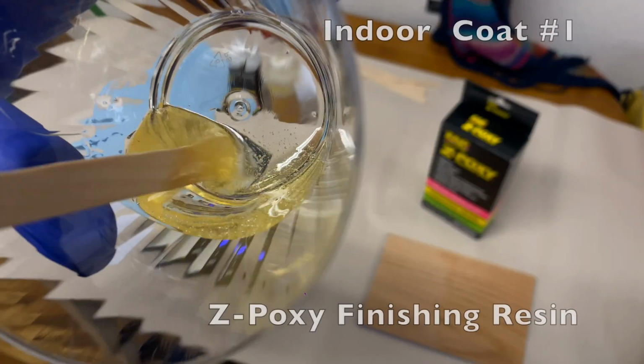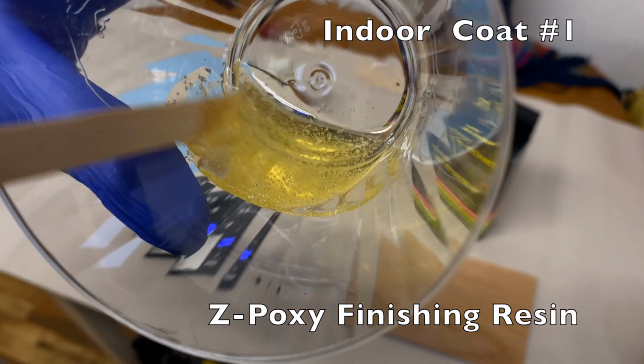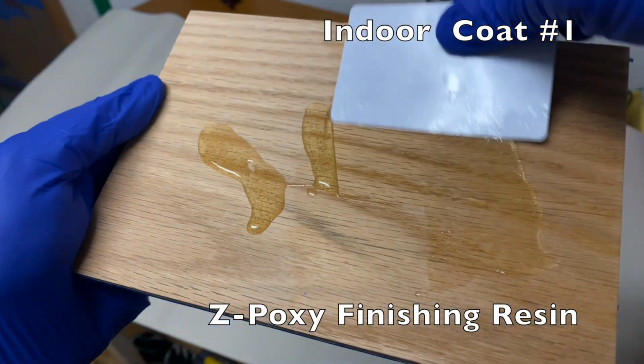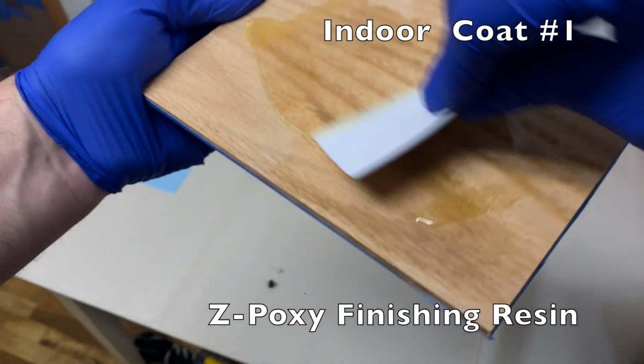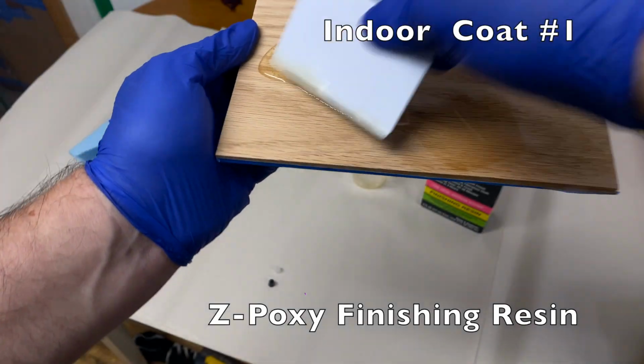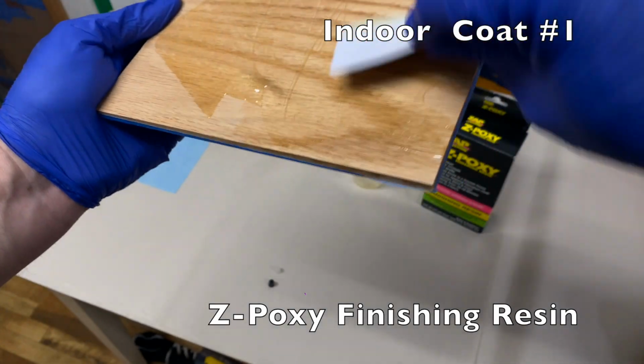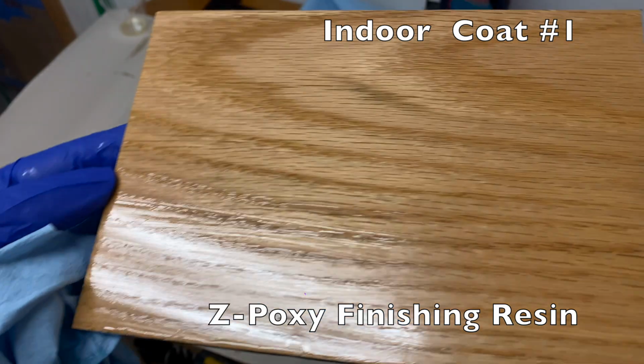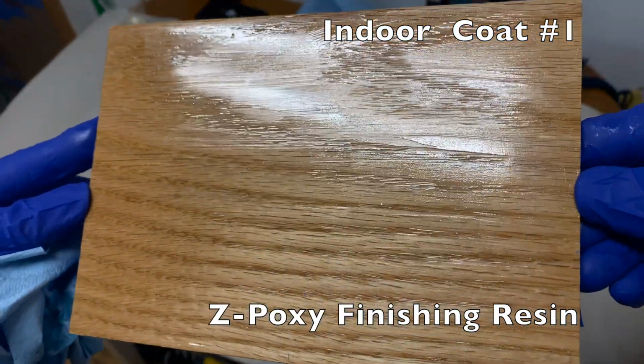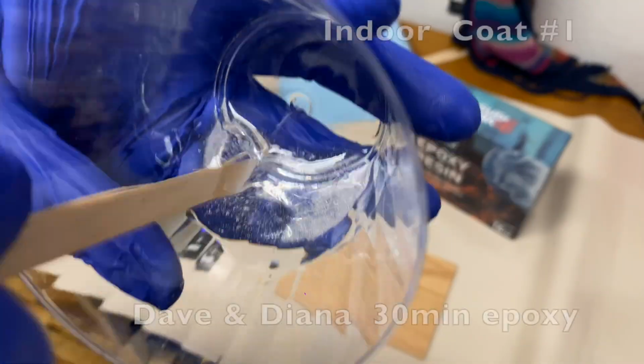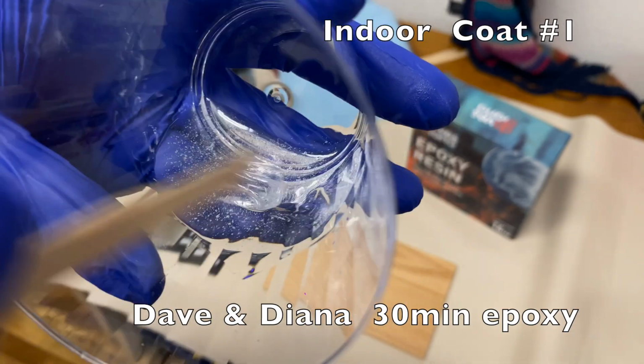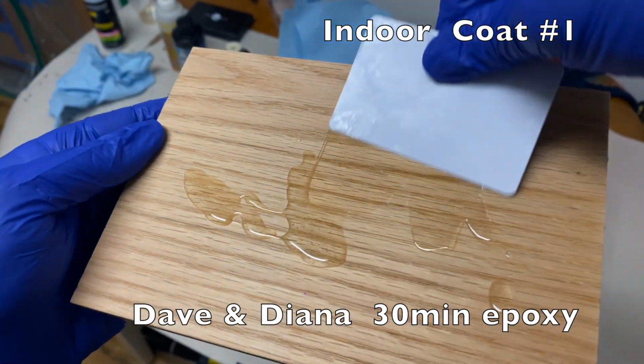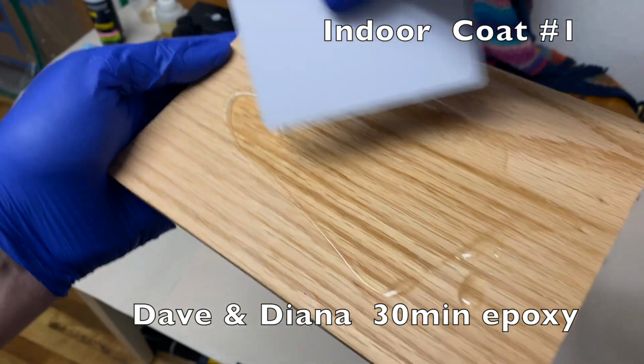So I've moved indoors to a room that's a little over 70 degrees, and it becomes immediately apparent that the Z-poxy finishing resin is a low viscosity epoxy, as it actually dripped off the board while spreading it around and scraping it off. This makes it possible to get a super thin coat with ease. The same held true with the Dave and Diana. It's a super low viscosity epoxy and easy to apply in thin coats.